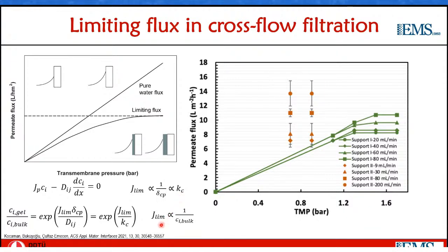And under identical hydrodynamic conditions, it's also expected to be inversely proportional to the bulk concentration of the colloid. The lower the concentration, the higher the limiting flux. So we first wanted to see if we can observe this with the cellulose nanocrystals. We did this on two different supports. One was a dense and transparent support that made visualization in optical microscopy easy. And the second was our actual porous support that we used in the membranes.